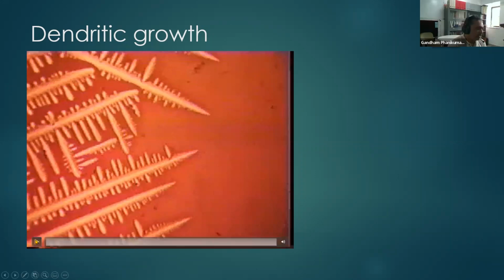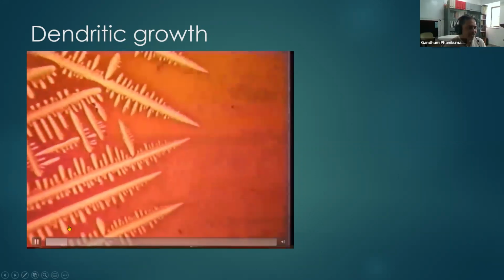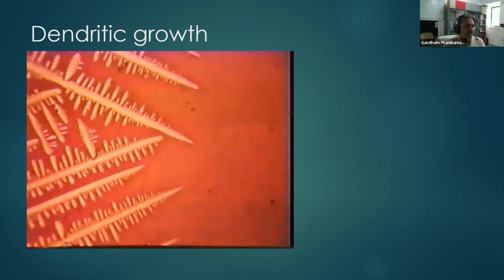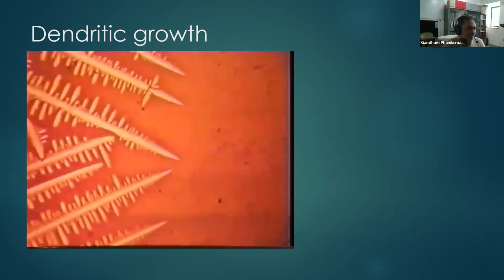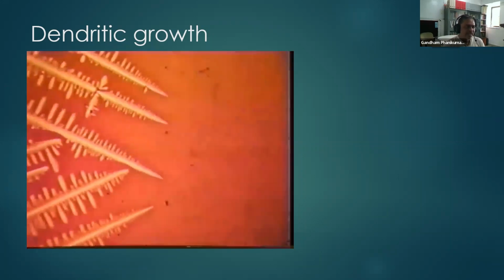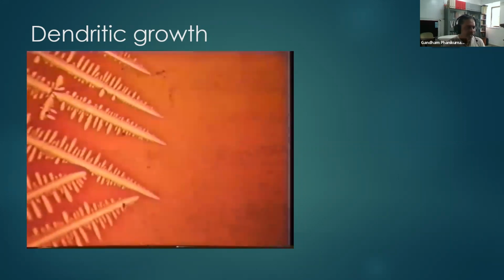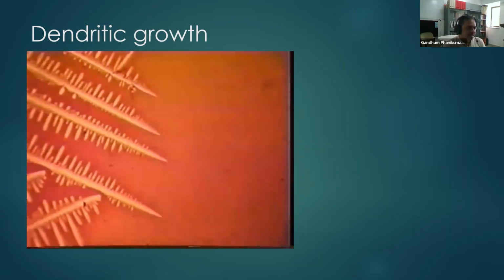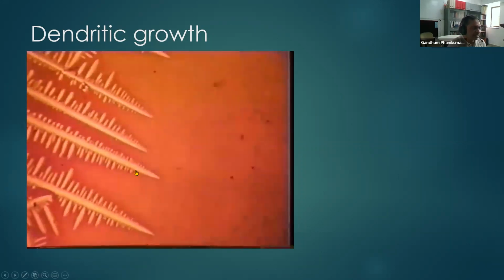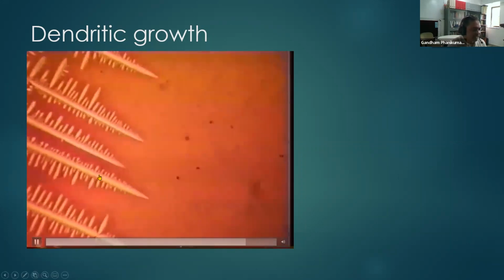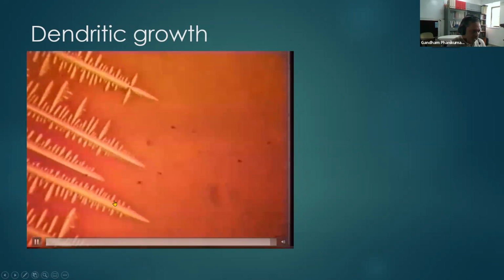Okay, so when you zoom into the solidification front a bit closer, you will actually see some tree-like appearances, which are also called dendrites. Nickel-based superalloys in particular are very commonly found in the dendritic pattern. The reason the dendrite pattern comes is because of anisotropy of its growth and surface tension.